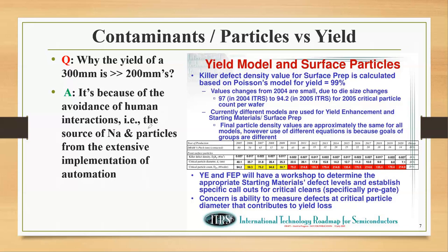And humans, we have sweat, even though we have a bunny suit. We try to be as careful as we can, but you still have sodium particles floating in the air, right? And the unknown particles from our human breath. So these will contaminate your wafer, because sodium will go into your wafer and become a mobile ion, and that will create shorts. You don't know what happens, but it happens all the time. That's why we have bunny suits. That's why we have clean rooms.